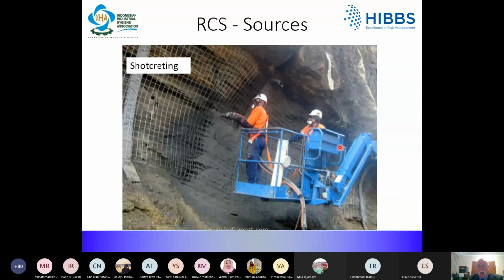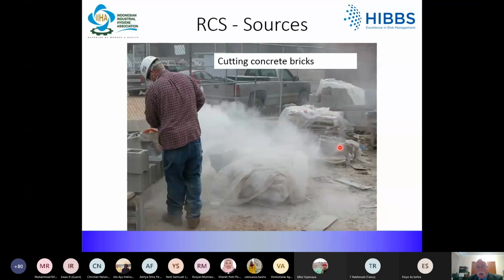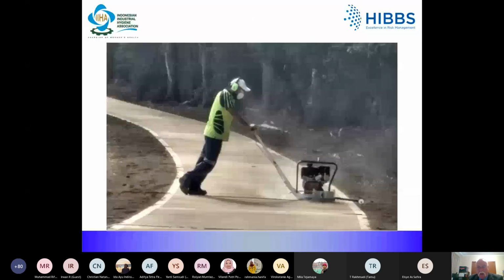Shotcreting, where you're spraying concrete onto other surfaces, and even though it's done as a wet process, has the ability to release quite significant concentrations of crystalline silica. You can see this bloke, he's cutting concrete bricks. There is no exhaust ventilation and no wet work, and he's generating quite significantly high concentrations of dust, which will be high in crystalline silica.